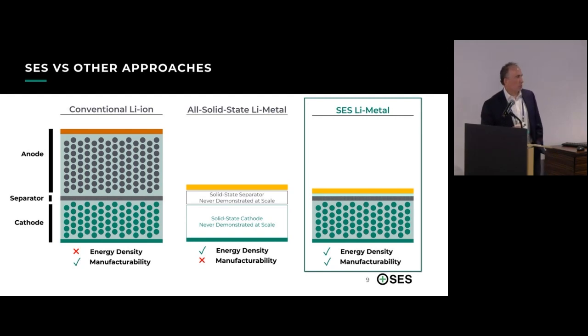If you look at our approach, we're basically replacing all those big black circles on the left, which represent graphite, with a thin piece of lithium metal, about 20 microns in thickness, so thinner than a human hair. And what enables the lithium metal to work is our electrolyte. And so just looking visually at it, you could see we can make a much smaller, lighter battery.